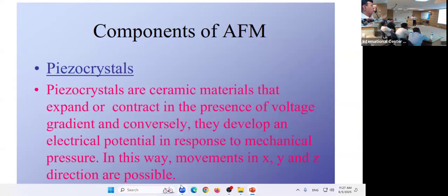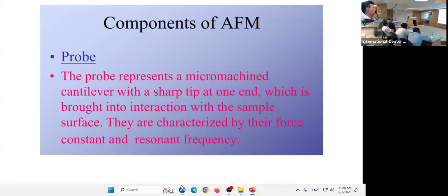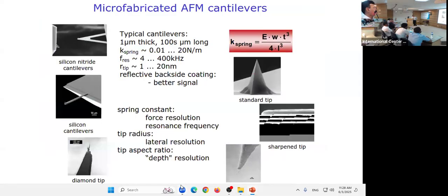This is actually a piezo-crystal, as I mentioned earlier, a material which can expand and contract in the presence of a voltage gradient. This is important for the creation of the images. And the probes, the cantilever, we already discussed. Every cantilever has a spring constant or force constant. So you should know the spring constant of your cantilever, because that is what you will have to report in your thesis and your publication. Normally it ranges from 0.01 to 20 newtons per meter.